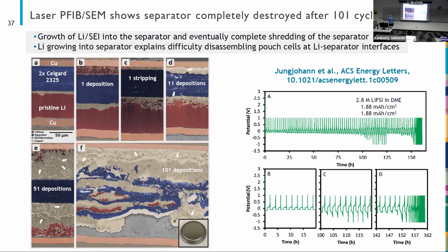Separators are there for a very particular reason, to prevent the two electrodes from shorting together. We really need that separator to work, and we need it to stay intact. So the fact that the lithium destroyed the separator through its growth process is not a good thing, and it explains why the cell failed. It's a little bit surprising that lithium was able to do this. It's a very soft metal, and so you wouldn't necessarily think it would be capable of destroying a polymer separator. But we do also have SEI capping all of that lithium, and so it's possible that that ceramic layer of the SEI makes the lithium hard enough to destroy this separator.